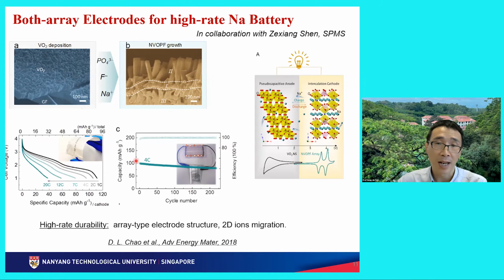They can light up an LED, an electric fan, or whatever tiny electronic devices, and the cycle number is 200. Actually, it's not that bad at high rates, because 4 C is quite high compared to the commercial 1 C rate. We want to emphasize that this is a strategy to realize high C rates. High C rate means fast charging and fast discharging. For example, 20 C means 3 minutes, so within 3 minutes the battery is fully charged. Of course, this battery is still a thin film battery compared to the bulky ones.